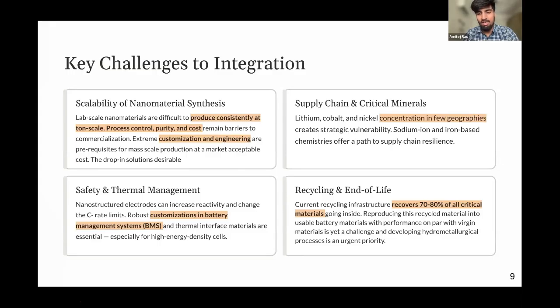So herein comes the competition. Taking a reference from lead acid batteries, 95%, actually 99% for the organized sector, of the lead, which is the active material, is getting recycled. Lithium ion still suffers from a lower efficiency of recycling, which can cause a burden, because we need more and more materials now. More and more mining should happen.